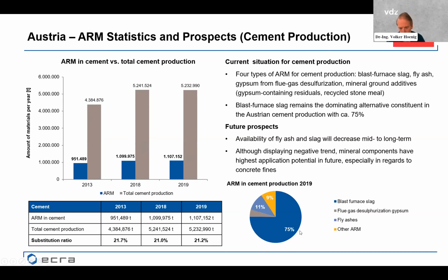was blast furnace slag. I mean, we know that Austria also has a strong steel industry today, and the blast furnace slag is mainly used in cement production. Furthermore, flue gas desulfurization gypsum has been used, and also some fly ashes, as materials in cement production. Also here, when we look at the future expectations, it is expected that fly ash and slag will decrease mid to long term. And you can imagine that slag representing 75% of these materials, this would mean that the total quantities of ARM would decrease significantly.